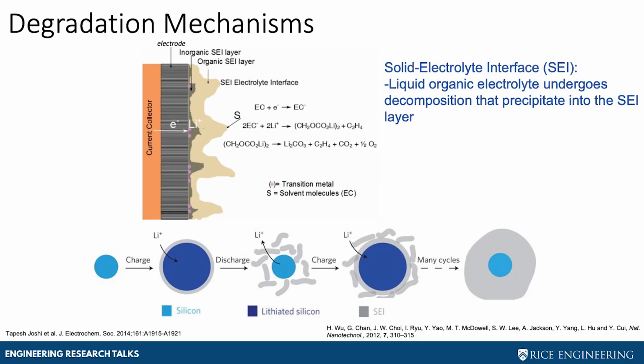So why is that? There are a lot of degradation mechanisms happening. Chemical reactions at these interfaces are causing degradation of the liquid electrolyte to form a solid electrolyte interface. And this solid electrolyte interface is actually insulating. It's preventing lithium from being able to diffuse into the battery material. And now, as we're cycling it, we have this organic matter there that's also being stressed. It ruptures, and it ends up causing a lot of chaos in our performance. And so this is why we saw that fade.